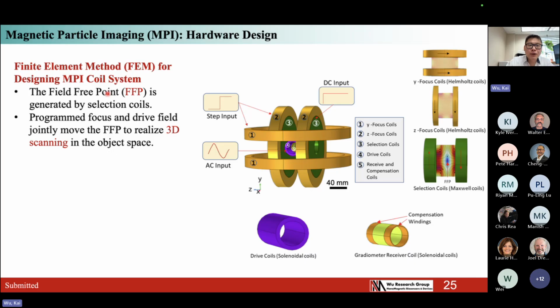So if you can recall the S shape of the superparamagnetic nanoparticles, when there's a DC field applied to the particle, the particle will be fully saturated by the non-zero DC field. So at this time, the particle is locked. When you apply the AC magnetic field, the particle will not generate any change of the magnetization upon the AC field because the particle is fully saturated by the DC gradient field.